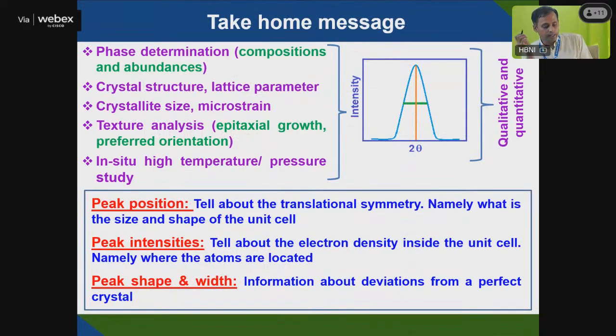Okay. So in today's class, the take home message is that we mainly covered X-ray diffraction instrumentation details, how it gives the X-ray pattern, and what information you get. From XRD, the first thing you get is phase determination, which gives you the composition and abundance: how much percentage is there, what is the composition, whether you prepared iron oxide, zinc oxide, or nickel or zinc nanoparticles. That can be identified by phase determination using XRD.